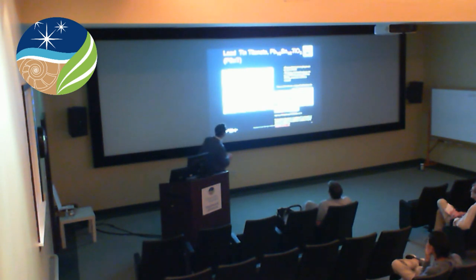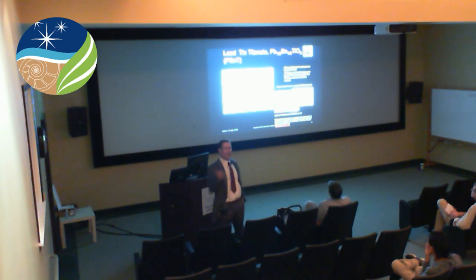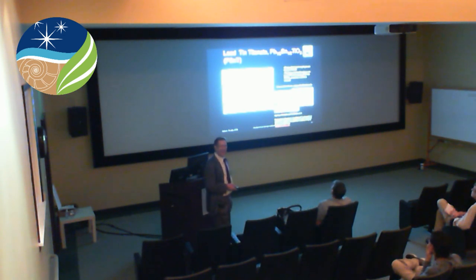So one reason that we started this small experimental program here is to do some stuff that we predicted but hadn't been able to convince anybody to do yet. Oh, it's done already. But maybe I can show this again. This is lead tin titanate, which hasn't been made yet, but based on this idea of pressure tuning, we came up with this material, which we predicted to have huge electromechanical coupling, higher than other materials, and if somebody could make it, say in thin film form, maybe we can use it to make better artificial insects that can fly around and spy on people. Well, I don't know that it's such a good result, but anyway, that's the kind of thing that these things can be used for.